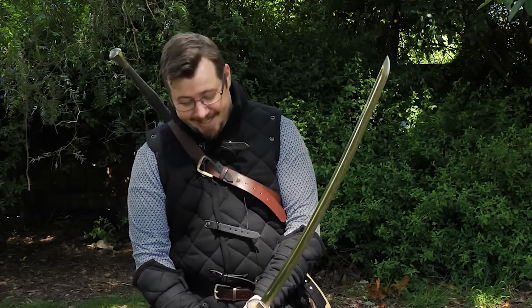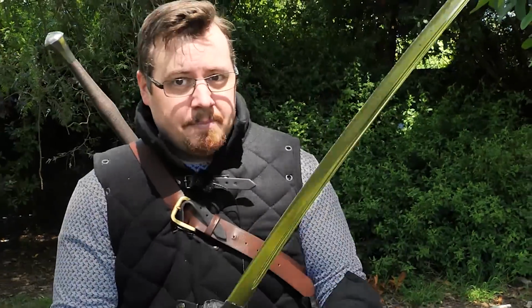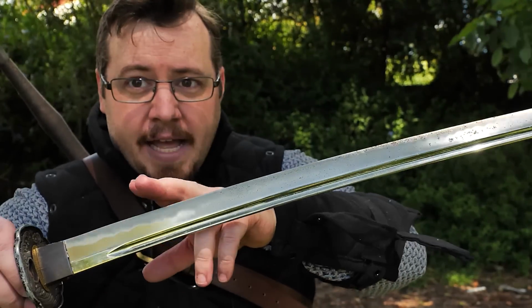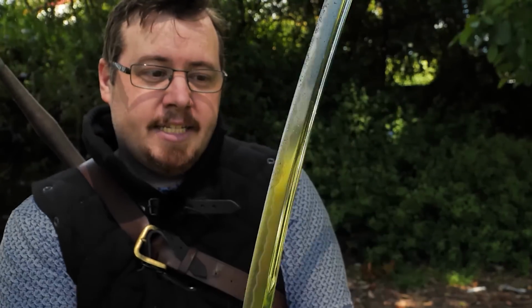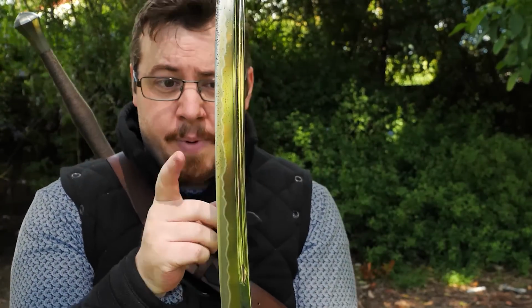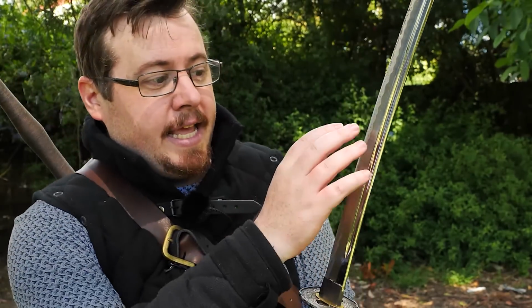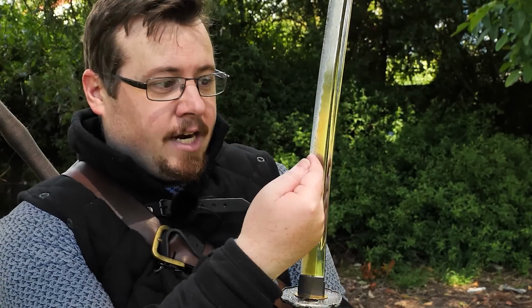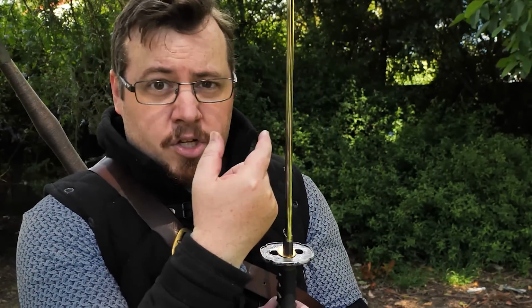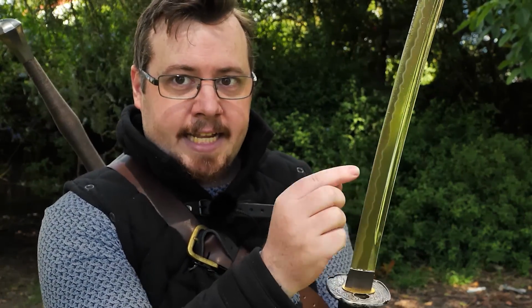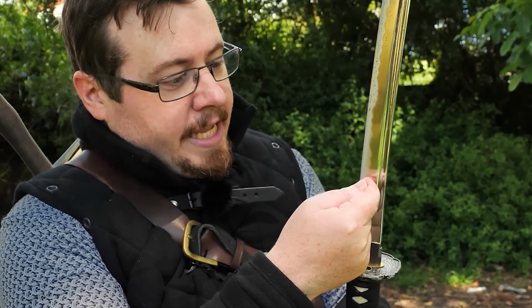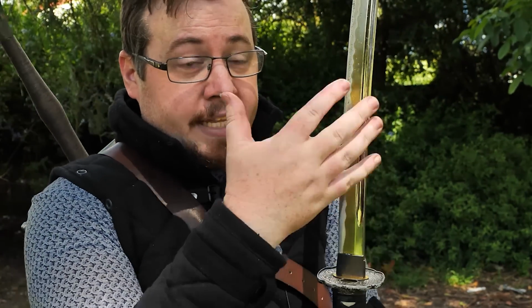And then people assume that it'll be resistant to bending, which is also completely incorrect. What differential hardening will do, and I'll come closer to the camera, is if you have a harder edge and a softer back, when you get a crack that impacts them, because remember, the edge is much harder on a katana than the other parts of the sword, when a crack reaches the part of the blade that's softer, and there's a really soft internal core on most katanas, which is closer to ferrite, and then this outer side jacket here is a pearlite type of steel, the crack will go in and it will stop. If this whole blade was as hard as the edge, that crack would go through and snap.